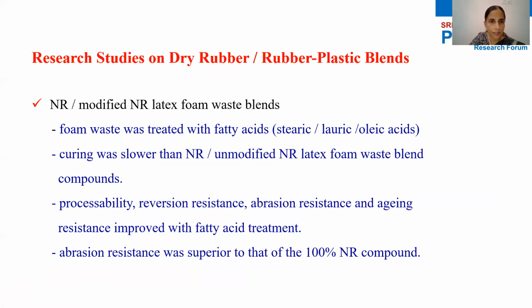Several research studies were conducted on dry rubber and rubber plastic blends. Natural rubber, modified natural rubber latex foam waste blends were produced. The foam waste was treated with the fatty acids, namely stearic, lauric, and oleic acids. As expected, curing of these composites was slower than the composite prepared with natural rubber and unmodified natural rubber latex foam waste. Processability, reversion resistance, abrasion resistance, and aging resistance improved with fatty acid treatment. Abrasion resistance was superior to that of the 100% natural rubber compound.